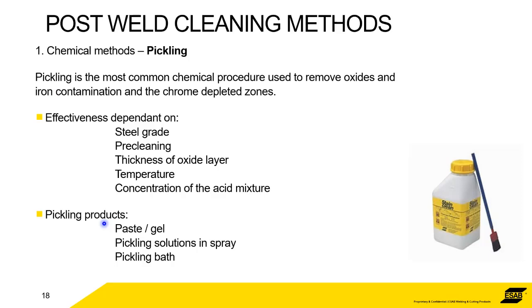Obviously, it's dependent on the steel grade, dependent on the concentration of the pickling media that you're using, but temperature and the thickness of the oxide layer all have an effect, but they can all be compensated for. Pickling products, paste and gel are the usual ones. You see these kind of applicators, just brush it on to the affected areas. But depending on the size of the piece that you have, you may even have a pickling bath.